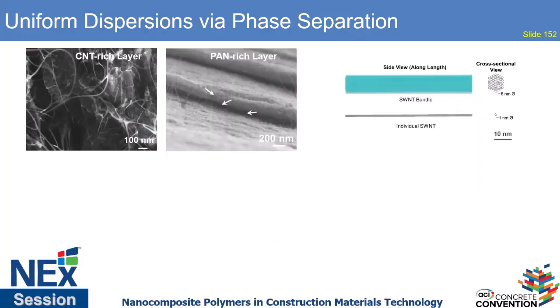So what we find is that in these different layers, and when we do a good dispersion, this is a typical nanotube-rich layer where the nanotubes have essentially been rejected by the polymer. And this is one where it's been captured by the polymer, and you can see very quickly the difference in the bundle size and uniformity of what's captured by the polymer versus what's rejected. So essentially you're using the polymer as a way to pull out the more uniform bundles and reject what is agglomerated and so forth, which is a great thing because it gets rid of those defects in your ultimate composite.